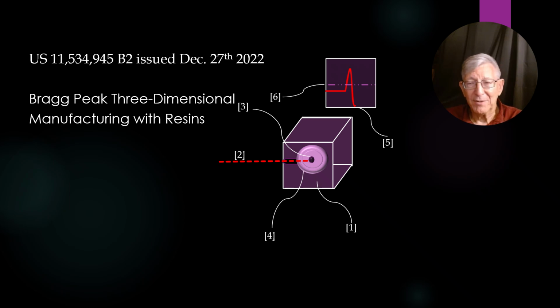And at that point, you have the highest probability of, basically, if you want to take a liquid resin and turn it to a solid resin, what you're doing is having a free radical or electronic ionic chain reaction occurring. And so you need a certain amount of energy density to get that chain reaction going. And if you manipulate your doses correctly, you can have a situation where nothing much happens until you get near the Bragg peak. And so the number 3 in this screen here is representative of forming a solid within this liquid at the Bragg peak.